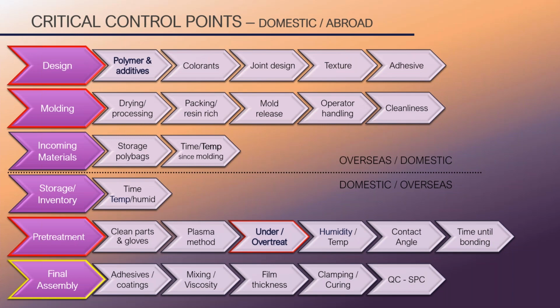Well, let's look at the factors that can happen during injection molding or primary processing. Drying of the material, particularly when they're hygroscopic and hydrophilic, are very important. During injection molding, how is the material actually packed? Is it a resin-rich surface or not? Depending upon how much glass fill is in the material, we always want to strive to have it uniform. During injection molding, is any type of mold release used? Silicone sprays. Even if they're not used on your particular machine, if it's used anywhere in the plant, silicone is very highly migratory and will affect everything.